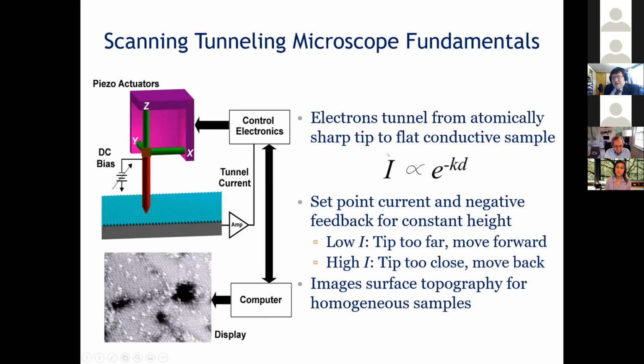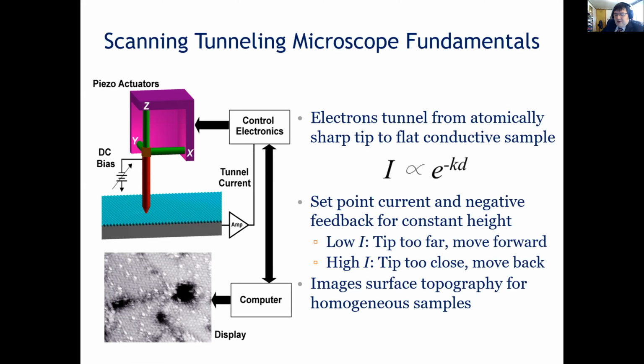So starting with scanning tunneling microscope fundamentals, the way the scanning tunneling microscope works is you take an atomically sharp probe and you bring it very close to a flat conductive sample, and you put a bias voltage between the probe tip and the sample, and that causes a tunneling current exponentially dependent on the distance between the tip and the sample. So if you get a little bit closer, you get a lot more current.